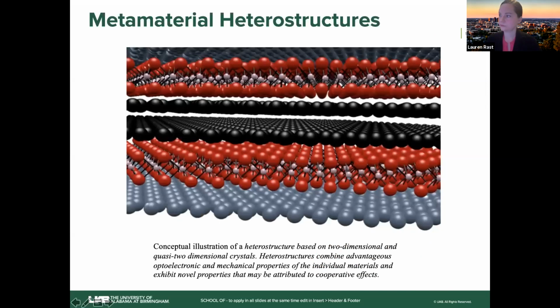So as we make progress toward more convenient production of these 2D materials, we're paving the road for fabrication of these tailored heterostructures on demand. And we can do things like materials by design for these types of heterostructures. So a 2D crystal-based metamaterial could combine, for example, the sizable band gaps of the transition metal-based 2D materials, which have band gaps that go from indirect to direct in single layers, with the unparalleled strength of graphene, and then the flat morphology of hexagonal boron nitride.